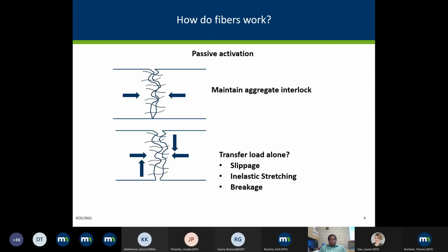A little bit, how do we expect these fibers to work? Really, the fibers work in passive activation, meaning you need the crack to form first. That's not going to prevent the crack. It becomes active once the crack comes about or within a joint system. So ideally, if this is a crack, we want it to hold the crack together.